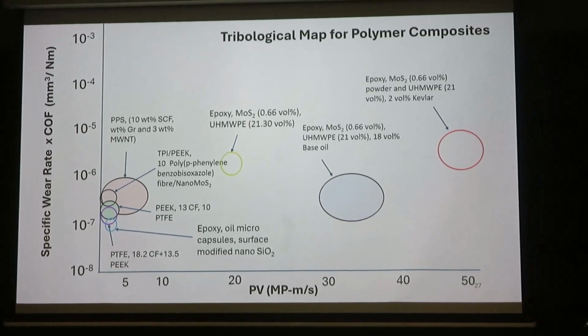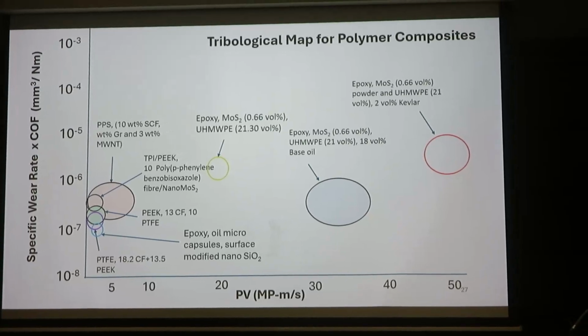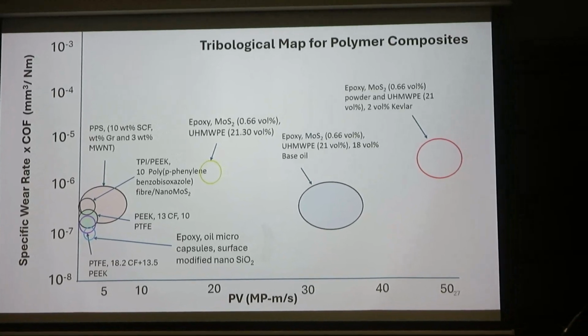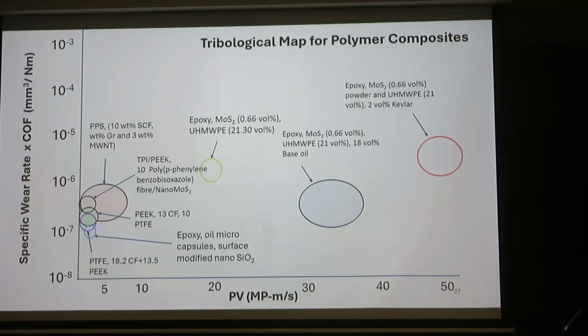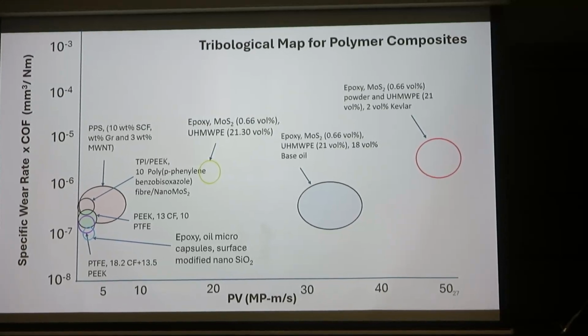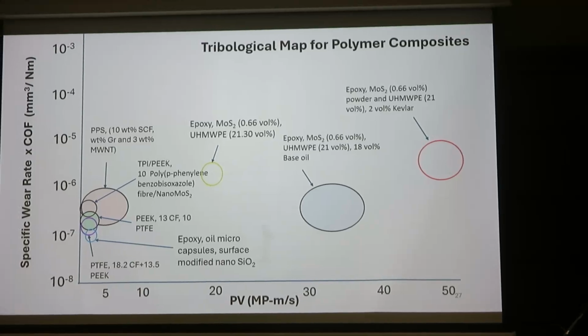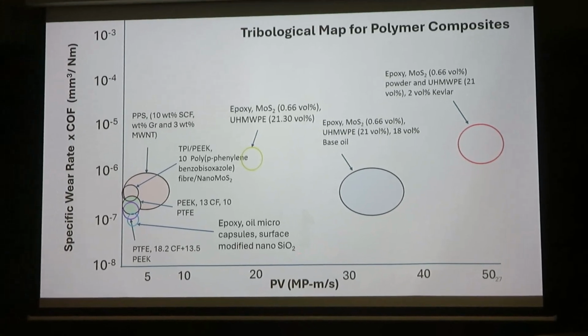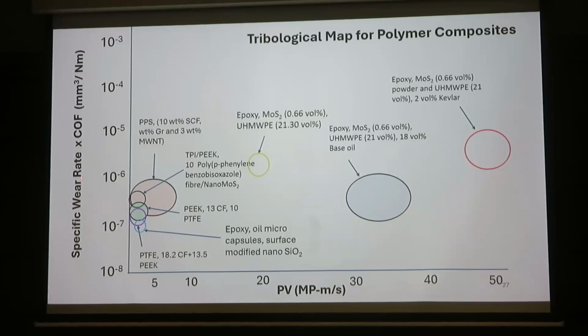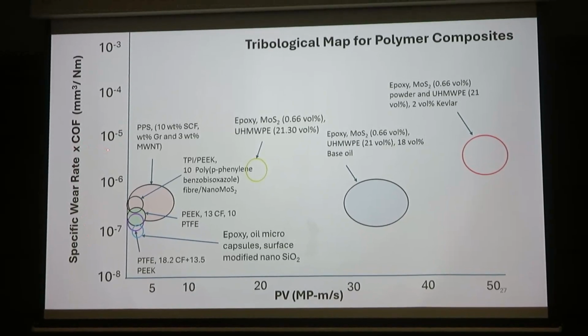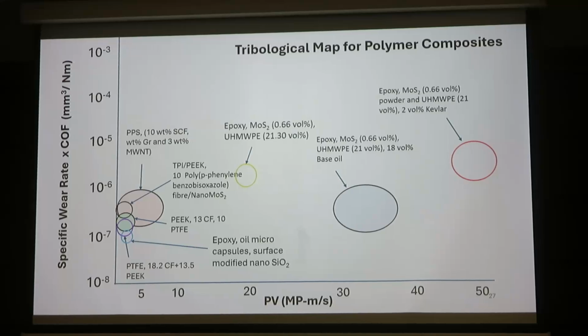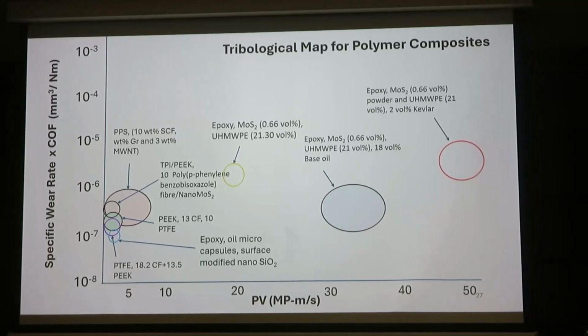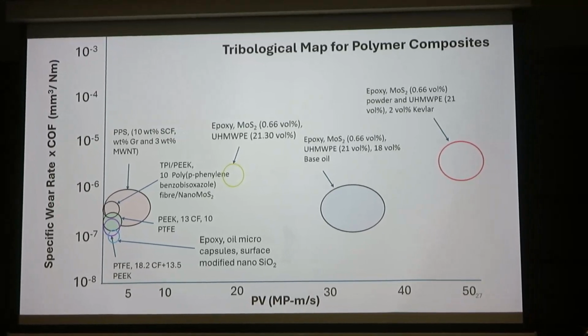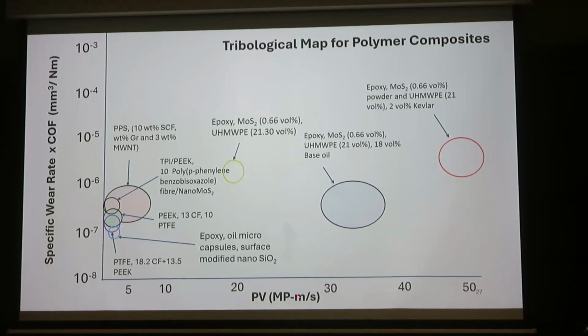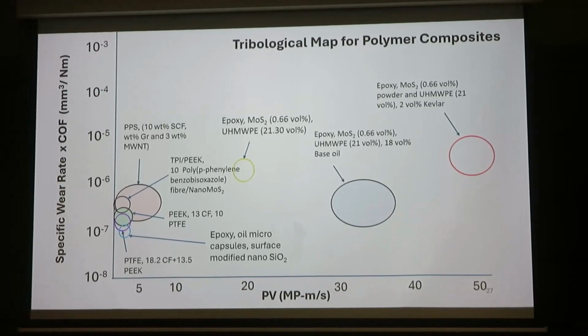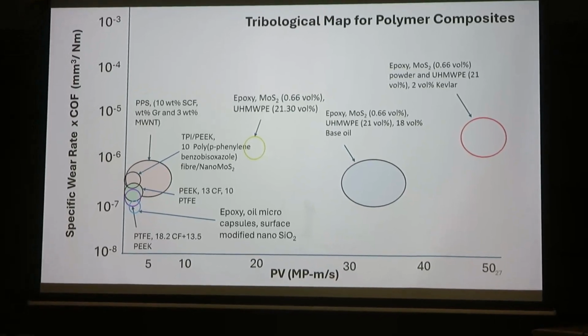So we were thinking about how we can plot this, because there are so many factors that are affecting. So for our material selection, how can we design? This can be one map that we can practice. For example, specific wear rate times the coefficient of friction. Both we are trying to lower, so if we multiply them, we want them as low as possible. Okay? And as a function of PV. We keep the PV because PV is a very good indicator of the performance.